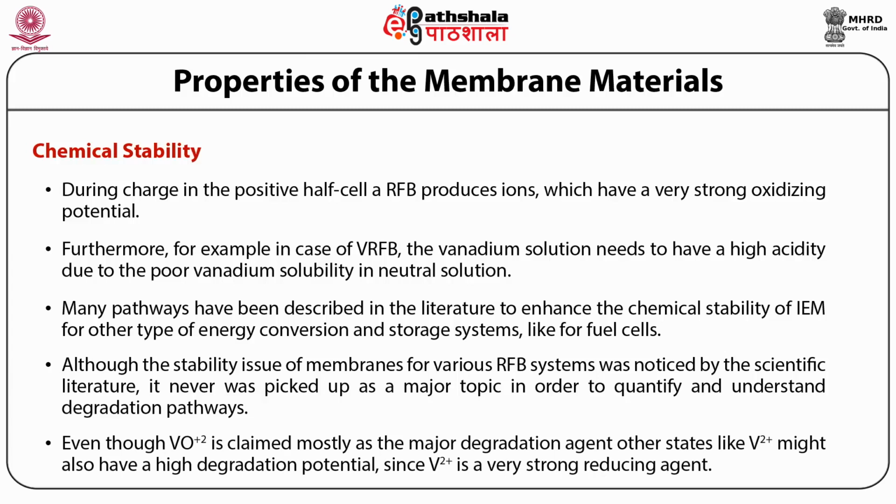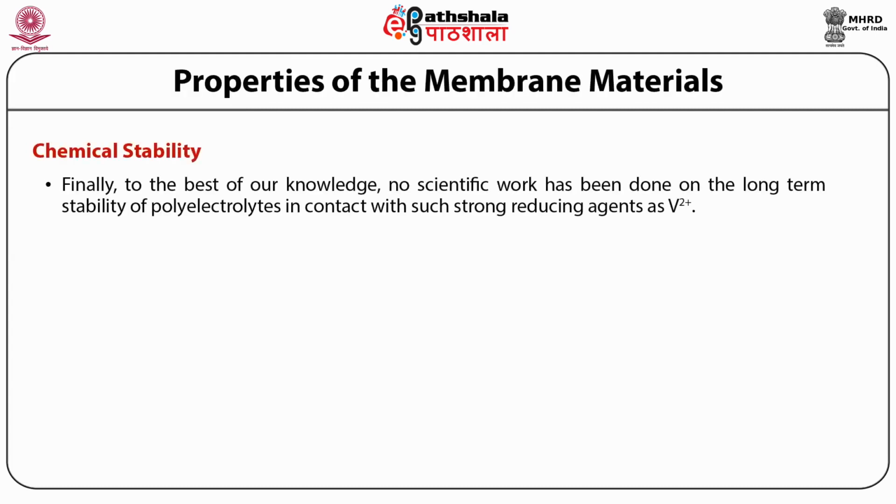Even though VO2+ is claimed mostly as the major degradation agent, other states like V2+ might also have a high degradation potential, since it is a very strong reducing agent. Finally, to the best of our knowledge, no scientific work has been done on the long-term stability of polyelectrolytes in contact with such strong reducing agents as V2+.